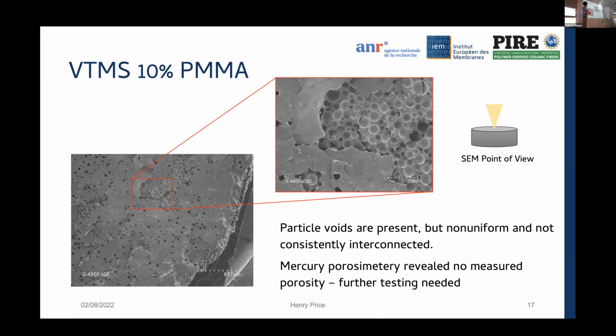And this gets to the heart of one of the issues with this process that I worked with all summer, because you're balancing the weight percent of additive you can add to the resin, which will increase the viscosity. However, you need a certain amount of this additive to get enough pores to have interconnected porosity.